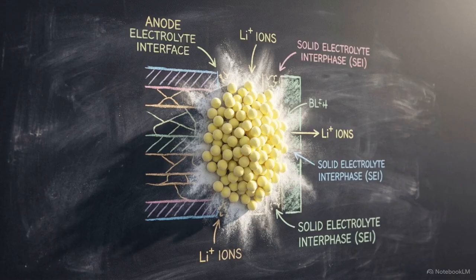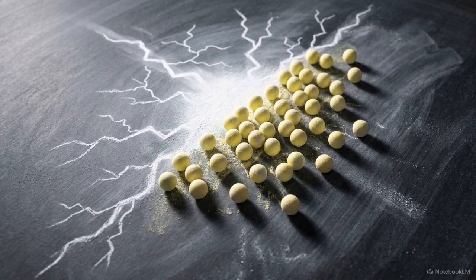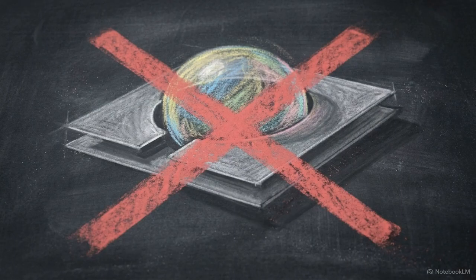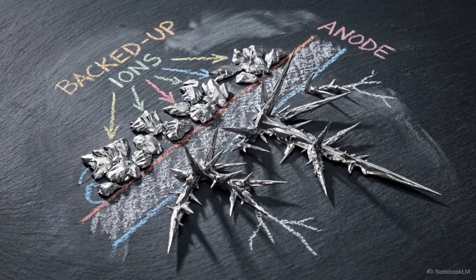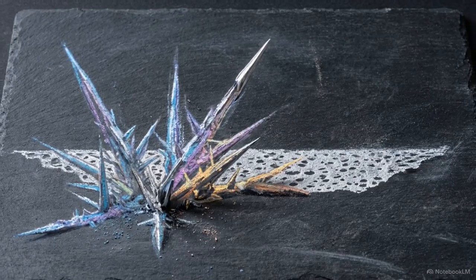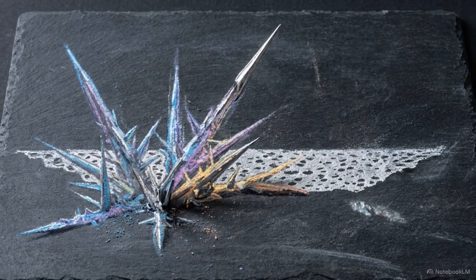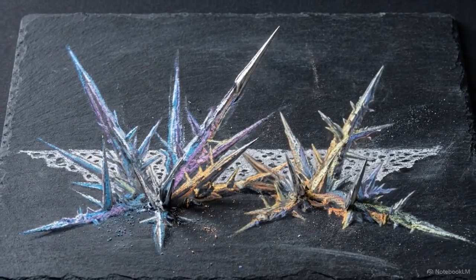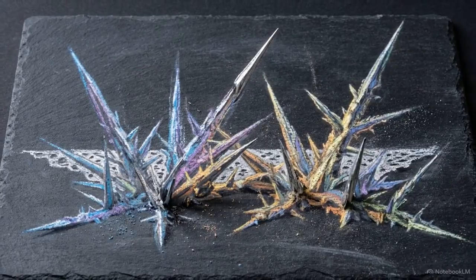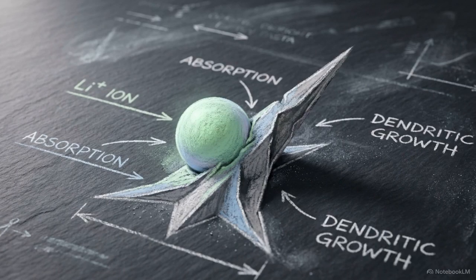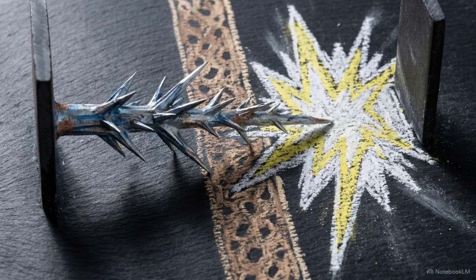When polarization forces the local overpotential to drop below 0 volts relative to the lithium reference, the system reaches its breaking point. Instead of safely intercalating into the graphite structure, those backed-up lithium ions undergo direct chemical reduction right on the surface of the anode. This results in lithium plating. Metallic lithium forms sharp dendrite spikes that grow outward and pierce the internal architecture of the battery. These dendrites permanently consume the active lithium inventory, killing the battery's capacity, and they create high-risk internal short circuits.